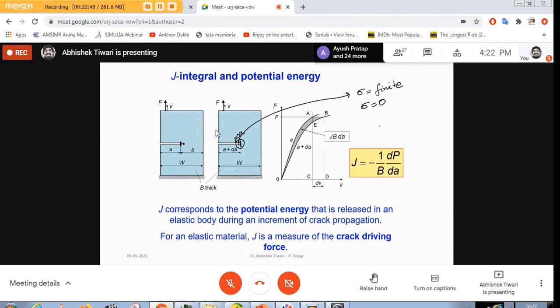Okay, so I was explaining that when the crack grows, there is some amount of unloading in the system, and that's where the J integral cannot define the true crack driving force. It can define something. What it defines is the resistance. What it defines is how much energy is released per unit crack growth, but that is also not true. It doesn't define only how much energy is released, but it is defining everything. It is defining the amount of energy which is released, plus it is also calculating the amount of energy which is consumed by the system in plastic deformation.